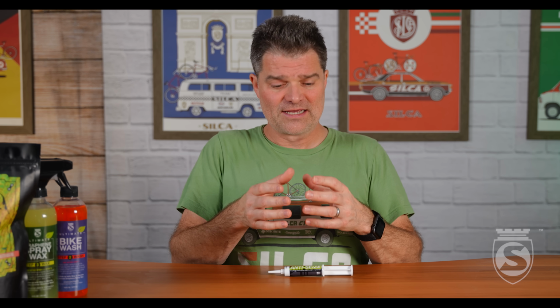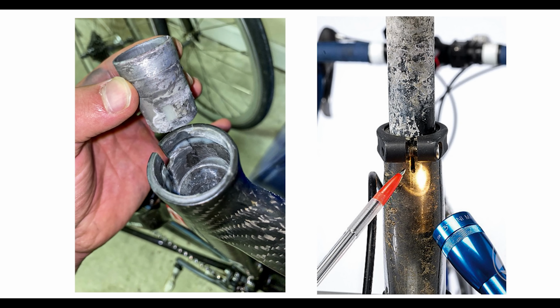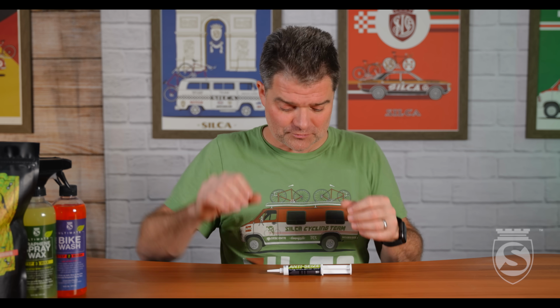it's not coming out. And even worse, what happens in some instances, and you can find amazing pictures of this on the internet, at the aluminum surface where it's turning into this aluminum oxide, it actually takes up more physical volume than it took up when it was just aluminum. And so the seat post is expanding in size and putting outward pressure on the tube, where essentially the seat tube has just sort of exploded in a location from this galvanic corrosion.